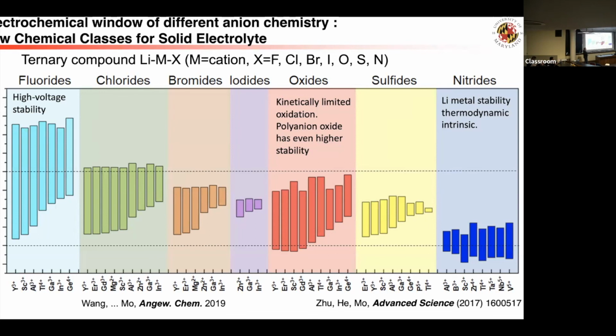Another thing is that people also want to do solution-based processing, but that goes into some technical details. Your cathode is still a composite. You mix the cathode active material, and you have an electron-conducting pathway and also an ion-conducting pathway. To mix that very nicely and have good materials utilization, solution processing usually does better. So that's another motivation: if you have good moisture stability, you can do solution-based processing to make the cathode composite.